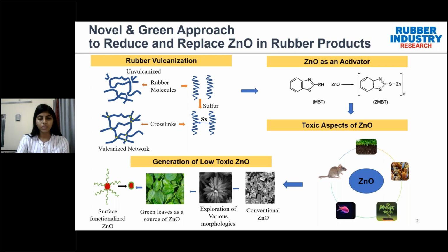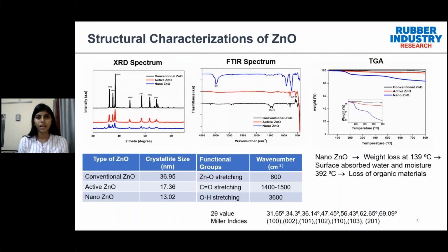From our side, we have explored replacing conventional zinc oxide with various zinc oxide structures, like active zinc oxide and nano zinc oxide. We performed structural characterization by XRD, FTIR, and TG analysis. From the XRD, the 2 theta values correspond to the typical Miller indices, confirming that the structure of the zinc oxide is hexagonal wurtzite. In the FTIR spectrum, prominent peaks of zinc oxide and OH were observed at 800 and 3600 in the nano zinc oxide.